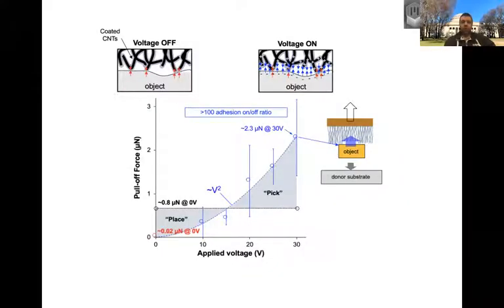And what I will show you is the stamp in this experiment where we pick and place a 100 micron or so micro LED. So not the smallest micro LED, but we pick it up and we put it down. And what you're seeing is no grabbing from the side, but just applying voltage and turning that off and on. And why this is interesting is first, because with voltage, we can scale the adhesion, the pull-off force, in a predictable way. The force equals voltage squared, traditional sort of electrostatic attraction. But also because when the voltage is off, the nature of these surfaces gives them a very low contact area with the object.